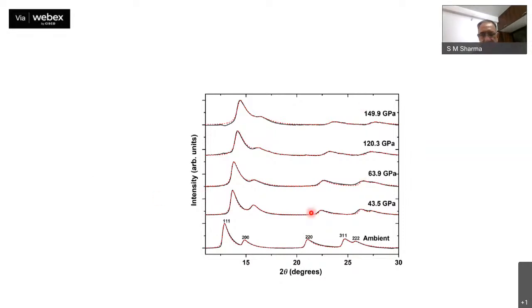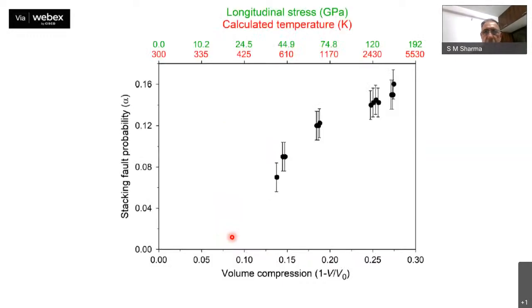In this case, we had to put in the stacking faults. If we didn't, the calculated peak, specifically the 200 peak, would be very different from this. The calculation would be somewhere here, the observed somewhere there. So by careful analysis of the data, we could show that the gold had a very large abundance of stacking faults at about 130, 140, 150 GPa.